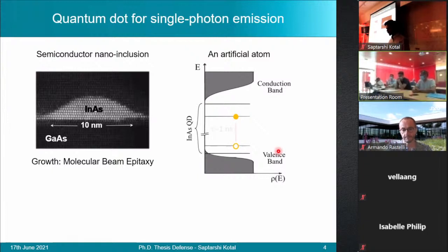After a certain amount of time, the two carriers may recombine, thereby emitting a photon, which in our case happens to be in the order of 950 nanometers. Now, the quantum dot must be re-excited again to be able to emit a photon of the same wavelength.